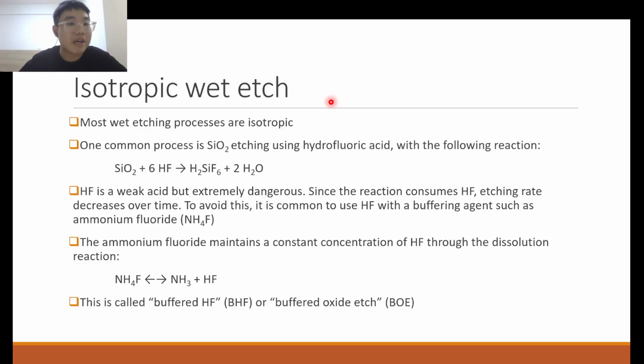So for example, if you want to etch SiO2 with HF to form H2SiF6 plus 2H2O, H2SiF6 is soluble in water, so you dissolve it away. You cannot say that the silicon dioxide downwards must react, but the silicon dioxide to the left and to the right cannot react. No, as long as it's not masked and it's in contact with your reagents, it will dissolve away.